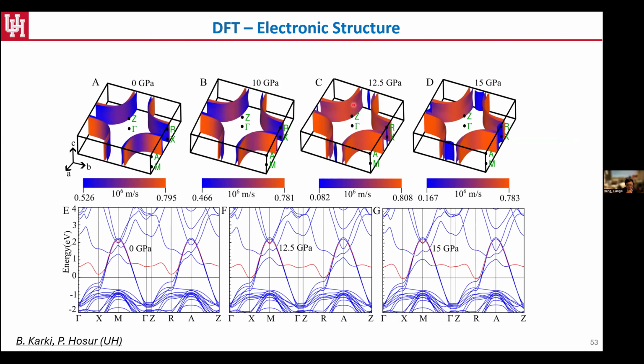Of course, we also have colleagues at the UH to calculate the density of states. It also shows that above 10 GPa, we do see an electronic transition similar to what happened in the BST case. So that provides another source that may contribute to the energy barrier.